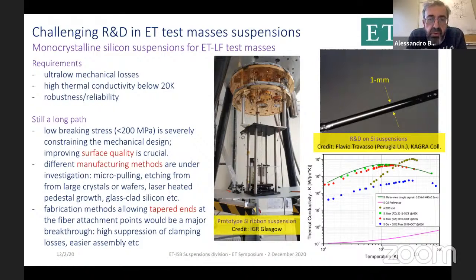Now, in all test structures that have been tested, the low breaking stress severely constrains the mechanical design. On that, we need to find ways to improve as much as possible the quality of the surface of the suspension fibers. This is the critical aspect. There are a lot of manufacturing methods under investigation. Making thin, very long fibers that have all these properties is difficult. So micro-pulling has been tested or investigated, etching from large crystals or wafers, laser heated pedestal growth methods, or glass clad silicon methods. You will hear tomorrow about this new technique.